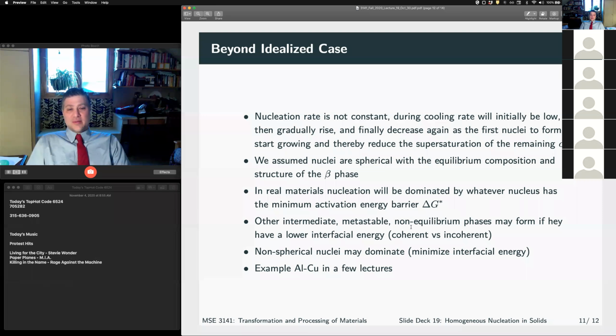Other metastable non-equilibrium phases form if they have a lower interfacial energy, right? GP zones and the other intermediate phases nucleate much easier because they have this smaller delta G star, even though they're not the thermodynamic energy minima. Okay. And we'll look at this for aluminum copper.